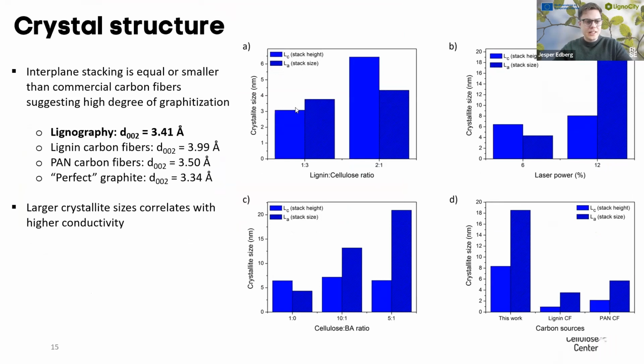Quite a lot of details on this slide. It's about the crystal structure, so basically the quality of the graphite that we're forming. I'm not going to go into the details, but we did see that we form very high quality graphite. So we have formed very big crystallites compared to many other publications, which is good because larger crystallites correlate to higher conductivity. And we also see that we have a high degree of graphitization. And in some cases, we could even produce graphene, multi-layer graphene, depending on the laser setting and the material composition.